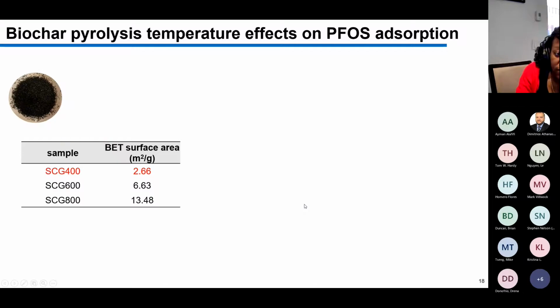So I'm going to present some data that we've collected about the biochar that we generated in the lab. That's a picture of what it looks like for different contaminants that are found in stormwater. So first, what we did was we wanted to take our source material, the used coffee grounds, and then burn the used coffee grounds at different temperatures to investigate how well those different temperatures remove or help to remove contaminants in the finalized product. So here we investigated temperatures of 400, 600, and 800 degrees Celsius. And then here's the surface area corresponding to those temperatures. So you can see these are pretty low surface area materials, and we were a little bit concerned about that.